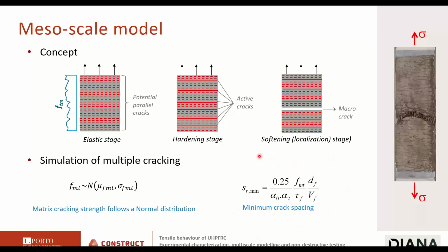For those of you that are used to reinforced concrete design, you see some resemblance here with the average crack spacing in reinforced concrete. You can think of alpha 0 times the volumetric fiber fraction as the effective reinforcement ratio that we consider in structural concrete. But then we use here an extra parameter, which we call alpha 2. If the fibers were rebars, so continuous filaments, this alpha 2 would be equal to 1.0. But the fibers are not continuous filaments; they have a small length, so they are not as effective in controlling the crack spacings as if they were continuous filaments. So this is a model parameter.